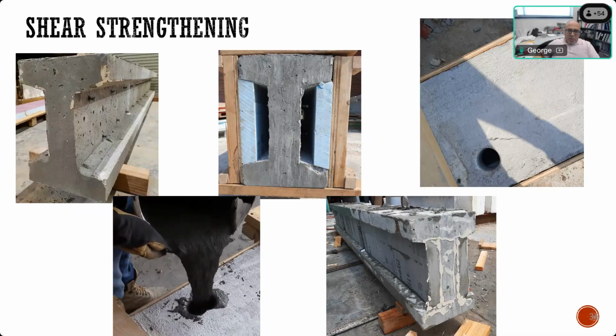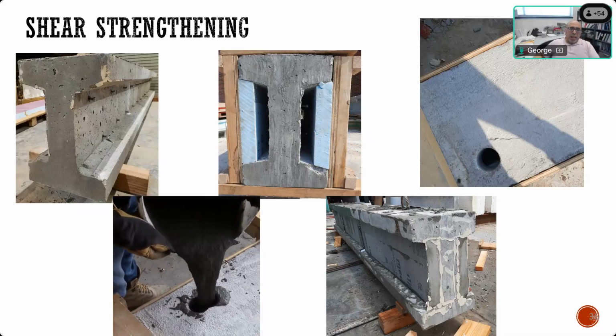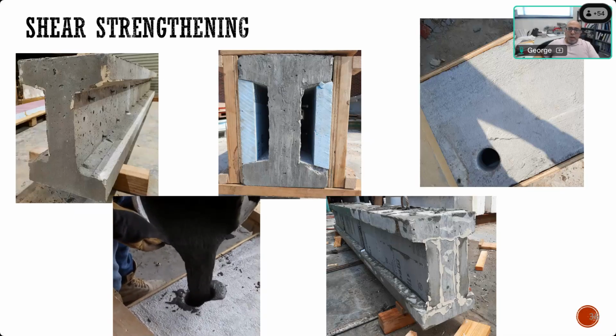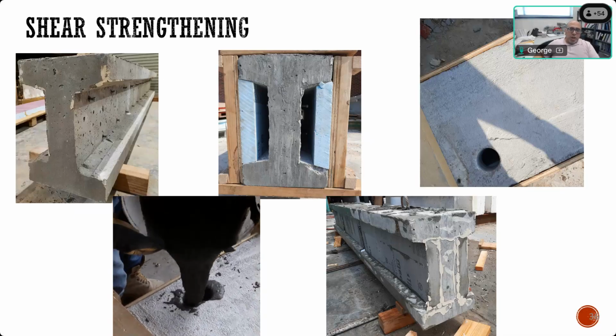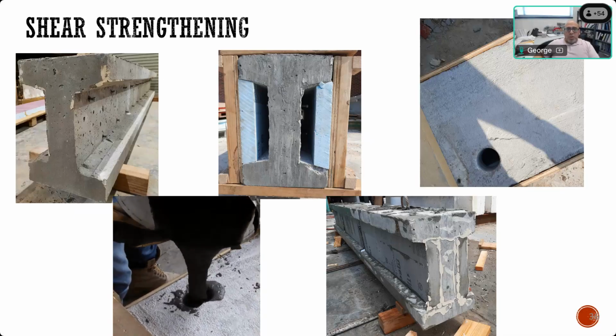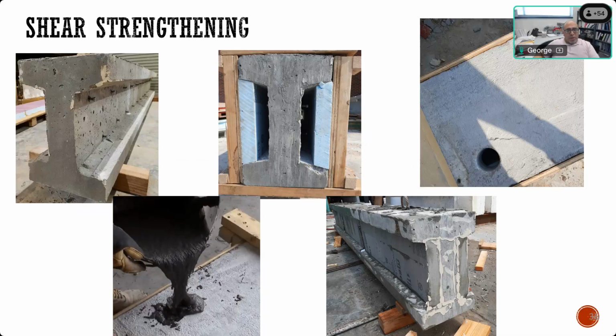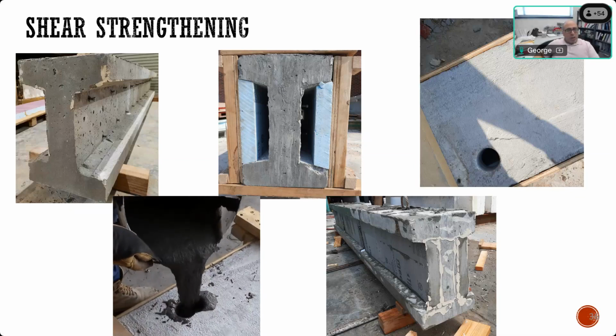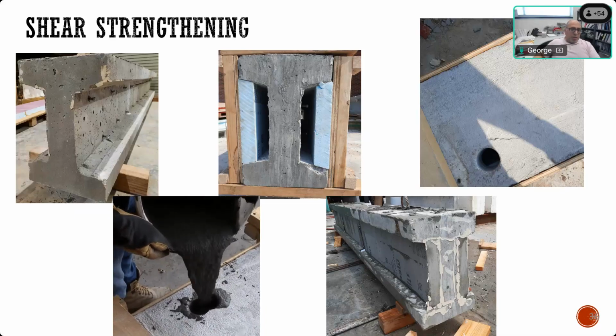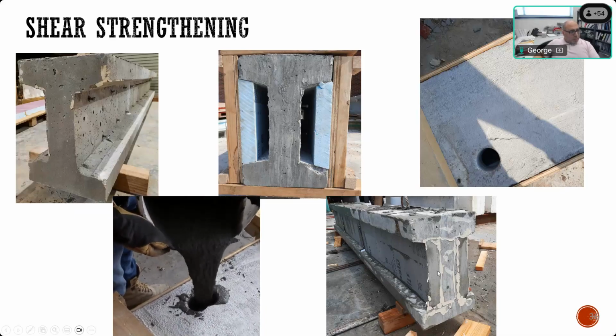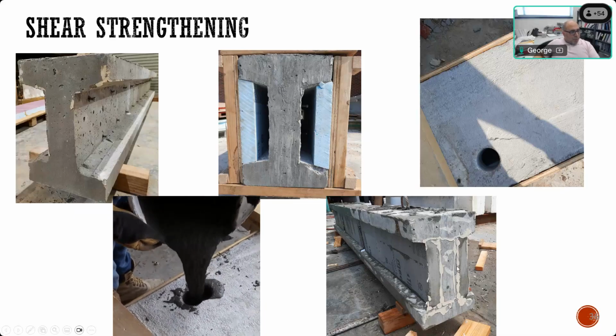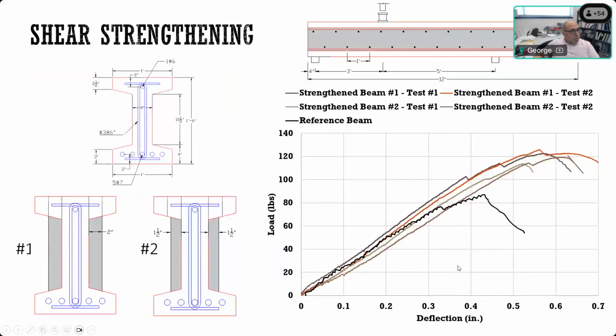We added some mechanical anchors, formed it for the 1.5 or 2 inches of UHPC, and made holes in the top flange so we could cast from that, and we ended up with a cross section of the strengthened girder that looks like the bottom picture here. And then we tested those girders in shear.